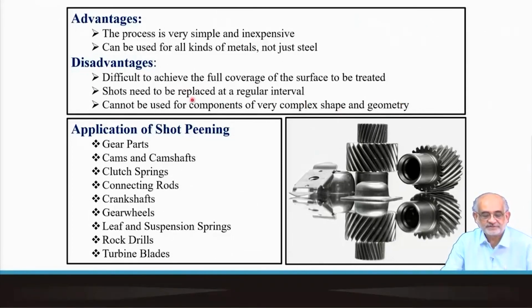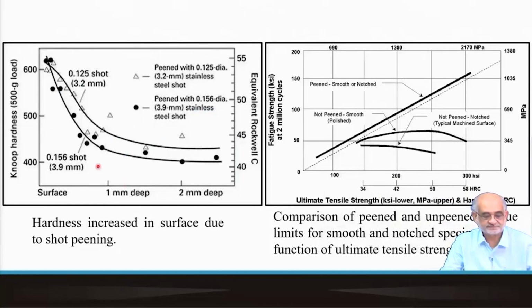As I already said, complex shape and geometry is an impediment to utilizing the shot peening operation. I have just listed a number of applications where shot peening is routinely used: gears, cams and camshafts, clutch springs, connecting rods, gear wheels, leaf and suspension springs. This is a very important operation because the springs continuously undergo such buckling and bending forces, because of which the surfaces undergo alternate cycles of tension and compression, and these are very typical cases where fatigue failure is very common. Then rock drills or turbine blades or any rotating or cyclically loaded components which are subjected to cyclic stress operations are quite common sites for developing such failures.